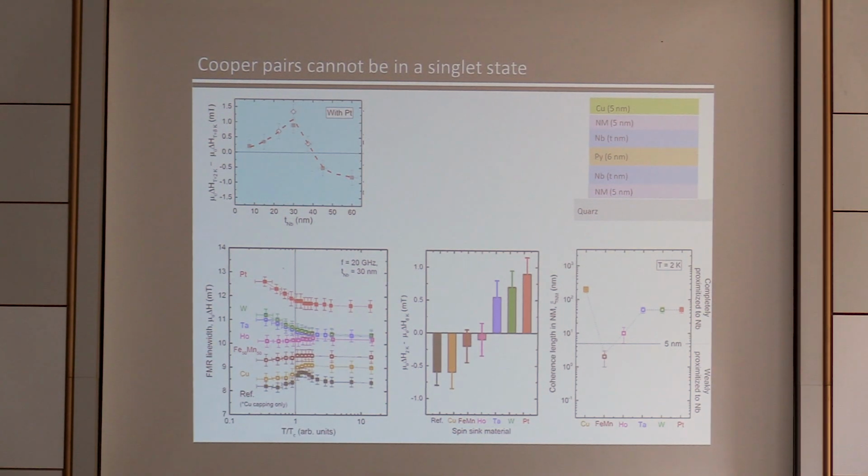In this case, since cross-Andreev reflection and electron co-tunneling are both initiated by single particles from opposite interfaces, we would expect tantalum really not to contribute a lot to these effects, because tantalum is not a very good reservoir of single particles, as there is a superconducting gap opening in it.